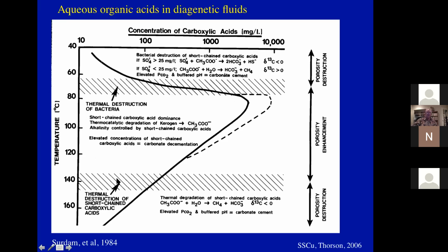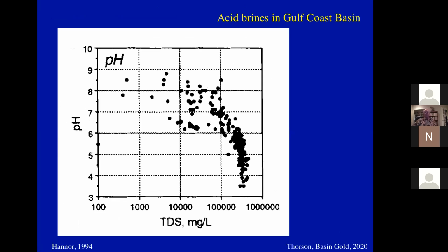And at higher temperatures, the high temperatures start breaking down the hydrocarbons and break down the acids at the same time. And so the amount of organic acids drops off once you get beyond about 140 degrees centigrade. So when you look at the brines in sedimentary basins, this is a plot of pH versus total dissolved solids in milligrams per liter from some work by Hanor. And you can see that once you get above 10,000 milligrams per liter, up into these 10% and higher total dissolved solids brines, they become quite acidic.